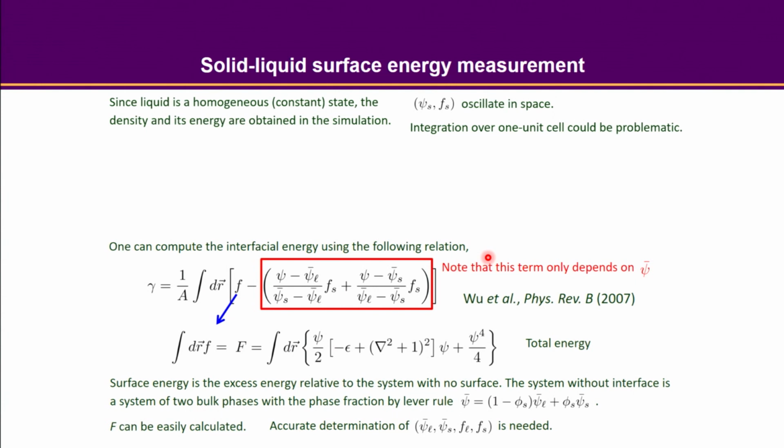The way to really accurately pinpoint that is to use the information we have obtained on the liquid side. Since the system is going to reach equilibrium in the end, the chemical potential everywhere, in the solid, in the liquid, even on the interface, is the same. It's all one number. And that number we have already known, because we know the coexistent liquid density, right? That's something we just read from our simulation. And there is a very simple relation for the chemical potential, which is a functional derivative of the free energy.